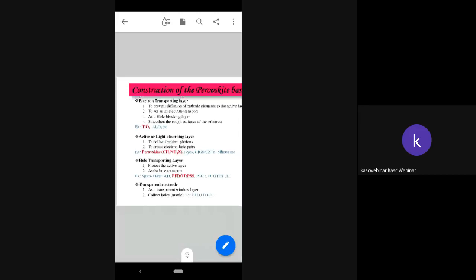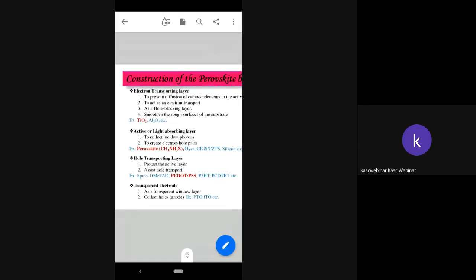Even though we are having a lot of challenges, the construction of perovskite solar cells involves preparation of electron transport layer, active light absorbing layer, hole transport layer, and transparent electrode. Let us discuss about different layers now. The first one is electron transport layer. The function of electron transport layer is to prevent diffusion of cathode elements to the active layer and to act as an electron transporter by blocking holes. For example, electron transport layer can be fabricated using TiO2 and Al2O3.